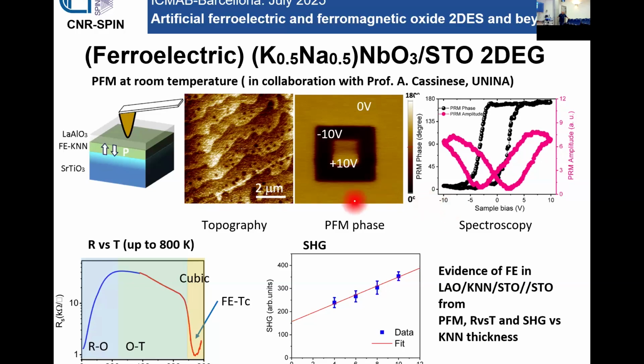Then we also perform other measurements, for example, R versus T of the 2DEG up to high temperature. We found the signature of the ferroelectric transition at the right temperature in the transport properties.